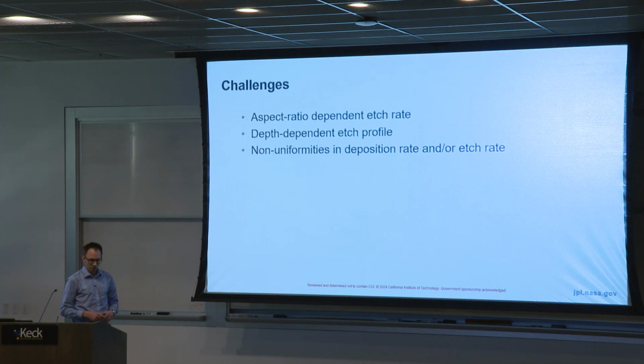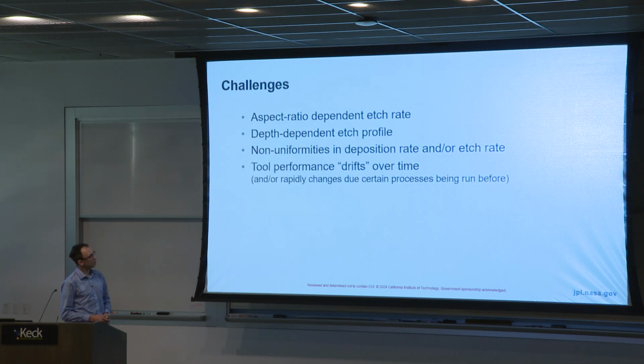Now, if you're hoping to do wafer scale processing of small metasurfaces, or if you're talking about making large scale, millimeter or even centimeter size metasurfaces, then non-uniformities in deposition rates and etch rates matter. Typically a lot of etch chambers etch faster in the center of the chamber on the wafer than they do at the sides, so even if you're done etching in the center, you might not be done at the edge of your wafer. And now, these are two practical and very hands-on challenges, but I think they're very important to at least consider.